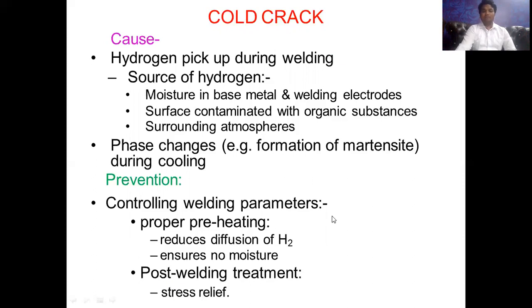Control welding parameters, proper preheating reduces diffusion of H2, ensure no moisture. Post-welding treatment, stress relief has to be done. In order to avoid the cold cracks, one of the methods is to do post-welding treatment. We call it post-welding heat treatment, to relieve the stresses present in the weld after the solidification.